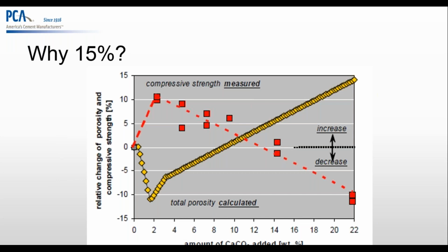Okay, so bear with me on this diagram. On the x-axis, you'll see the amount of limestone in percentage that is added to the system, ground limestone. On the y-axis, it would be the porosity, okay? And the red dots are the strength. So if we start at 0 right here, we start adding a ground limestone to the system, right? The OPC, we start adding limestone. Up to 2-3%, you can see that the compressive strength increases, the porosity decreases, which is very good, right? But what we're looking for is an equivalent product. That's how much limestone can we add to the system in order for it to be equal to OPC.